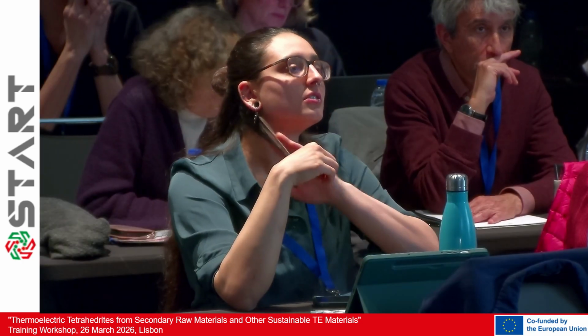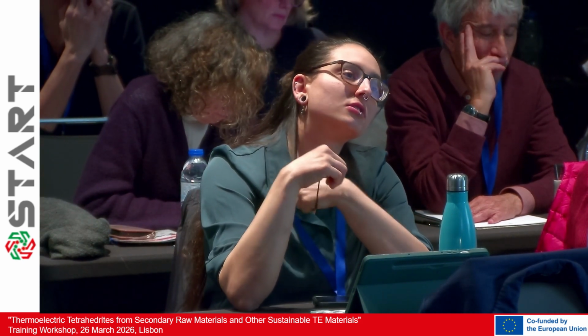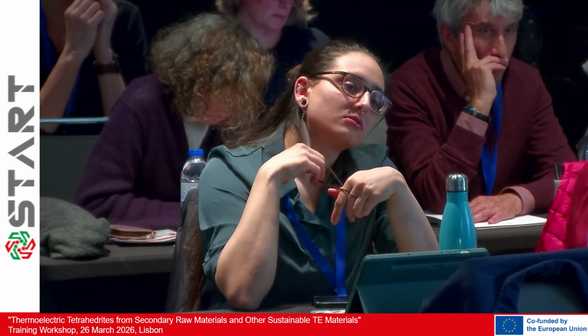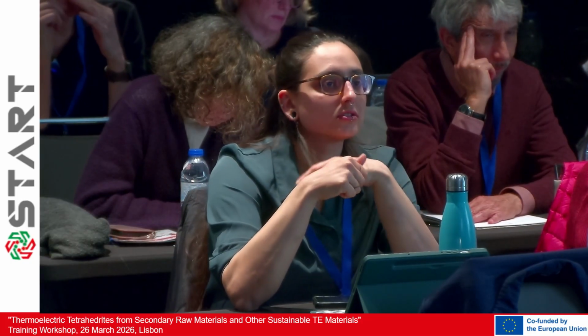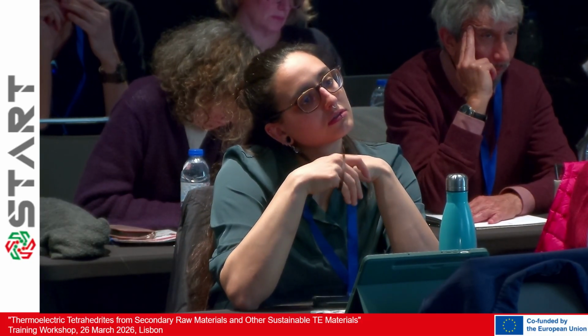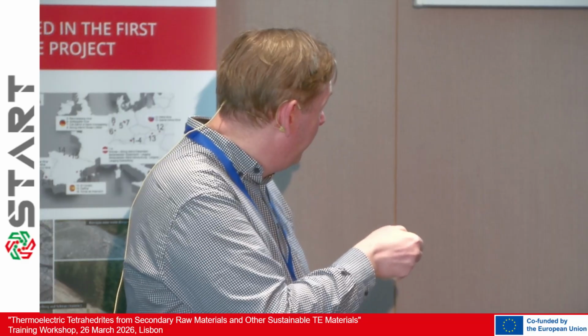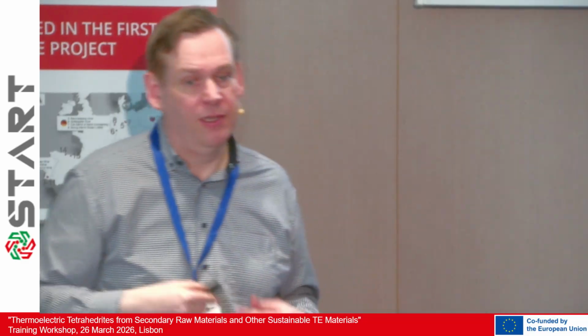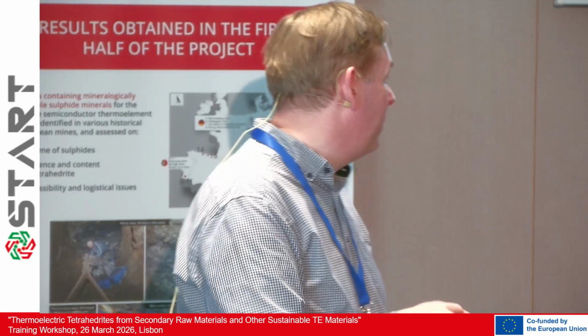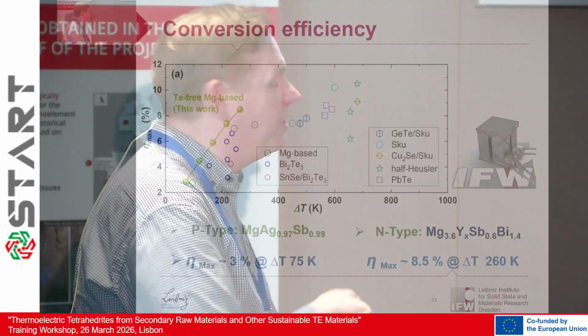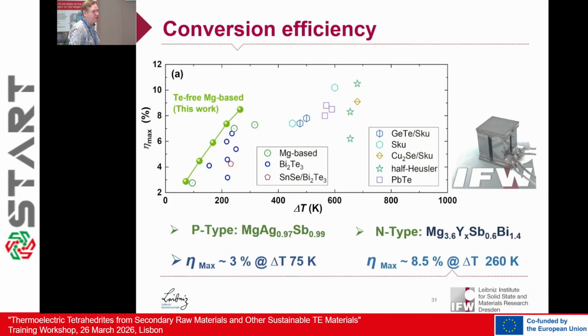After doing all these optimization steps, you can see here we have an efficiency of 8.5%, for example, on these modules, when we have a temperature gradient of 260 Kelvin applied. And even if we have moderate temperature gradients, 75 degrees, so just heating the hot side up to roughly 100 centigrade, we have 3% efficiency already. And this is usually, I think, the 3% efficiency you obtain with most commercial bismuth telluride-based modules when you apply a 200 centigrade or 150 centigrade temperature gradient.